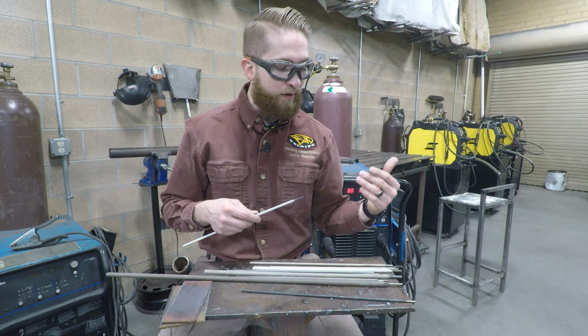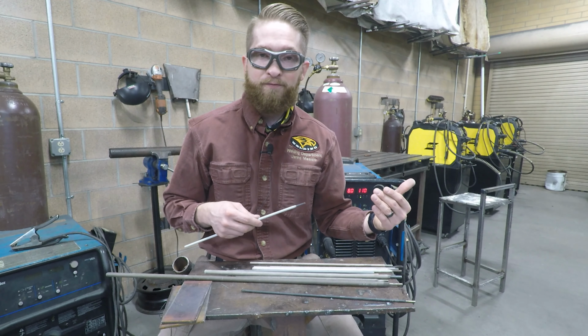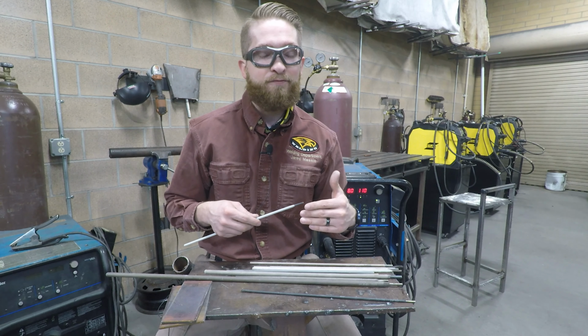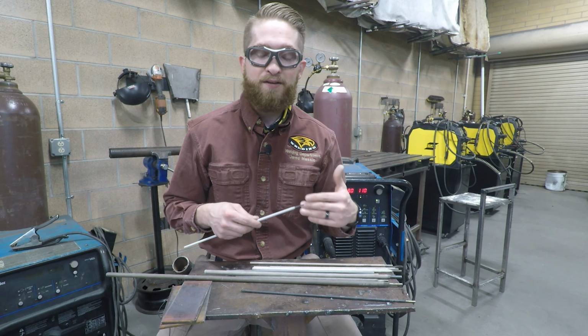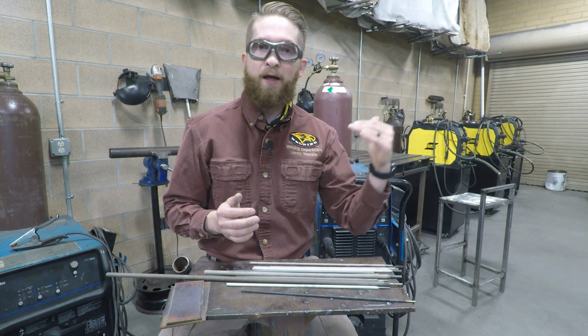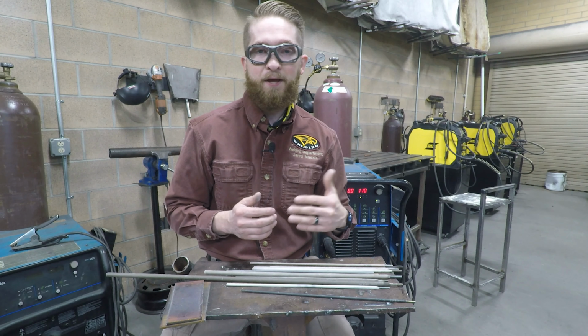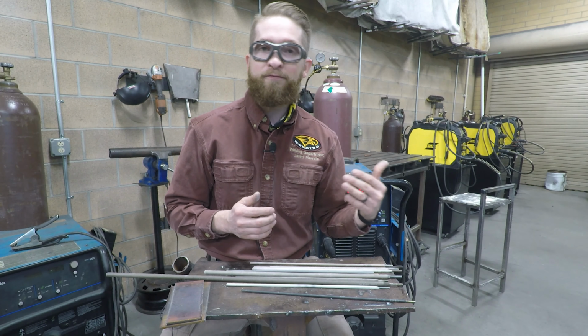It doesn't always work. Running 60-10 at 125 versus 70-18 at 125, you're going to get drastically different results, especially if you're welding on different thicknesses of material. And so we want to make sure that we try and set our machine up appropriately. Now, when we're welding on this 3/16 material, which we have an abundance of here at the shop, our 70-18, while it will still run at 125 and you'll be able to lay a pretty decent bead, it will be very hot. The amperage is a little high for that thickness. I would recommend going down to maybe 115 instead of 125. And then we'll go from there.